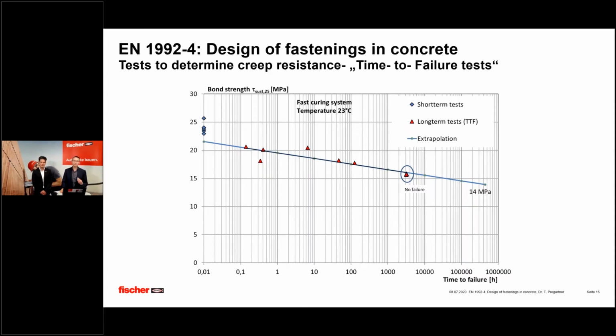One possibility is that you work with a relatively low sustained load, with a low creep load, and you measure the displacements of your anchor over time. Finally, you do an extrapolation of your displacement, and then you define a limit of maximum displacement, which you allow as safe. And you say, okay, if I stay below this limit, then my anchor is suitable for sustained loading.